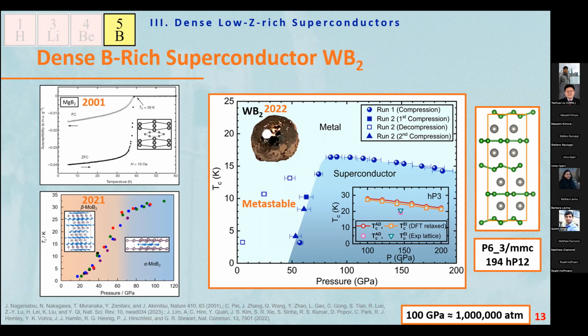But the theory calculation suggests that they should have the MgB2-like structure, but the tungsten diboride itself at ambient pressure is not an MgB2-like structure. It's on the right side of this figure, it's hP12, which has a buckled layer of boron. It's not flat. But the theory calculation is a flat boron layer, like the MgB2 structure. So at this point,